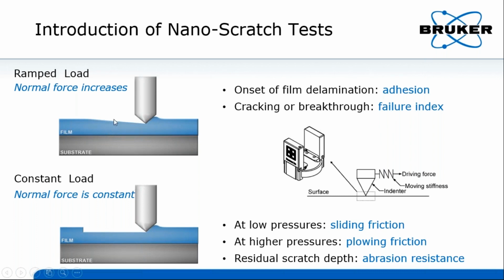A ramp force scratch test is probably the most common type for testing the film's adhesion. During this type of test, the normal force is increased continuously while the probe moves laterally. As the probe penetrates deeper and deeper, increasing stress is placed on the probe and the substrate interface. At a certain point, the interface fails and the film delaminates. If the film is brittle, events such as cracking or chipping may also be observed.